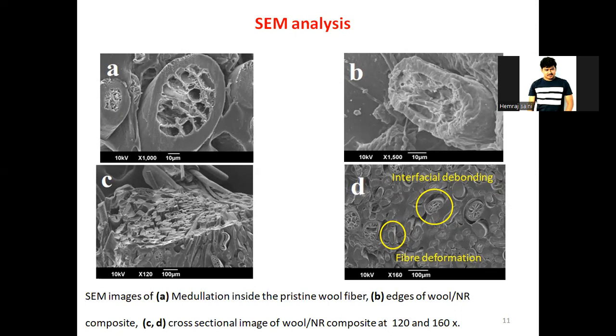And B is the edge of the wool/NR composite. C and D are the cross-sectional images of these composites. What I found is that in the cross-sectional images you can see the wool fiber. This is actually the tensile fracture surface of the composite. We found the medullation, you can see in figure D, the fiber medullation. There are some fibers we can see without medullation also. Some fiber deformation is observed because when we applied some pressure, the circular shape of the fiber became oval. So this is another difference that we observed.